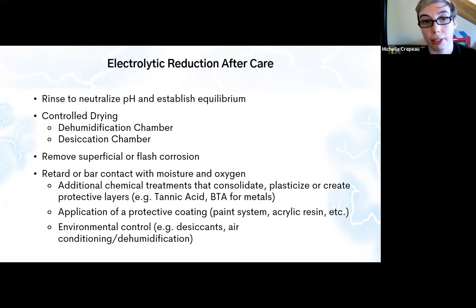And of course, electrolytic reduction, although it definitely prolongs the life of our artifact, particularly by removing chlorides and that effect of desalination and making it more consolidated and more physically and chemically stable, your iron artifact from your typical marine environment is never going to be a done deal. It's always going to be at risk of further corrosion and further degradation. That's just because it is in contact with an environment that has a lot of atmospheric moisture in it, and that also probably still has some residual electrolytes present.